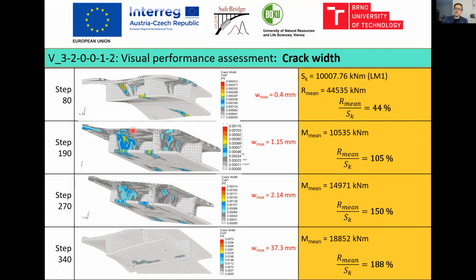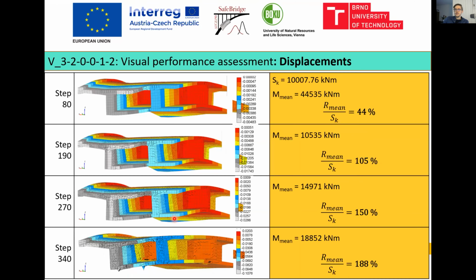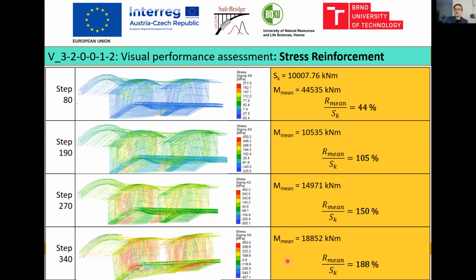You can see here that at step 80 the shear cracks are dominant, but then the concrete slab at the bottom becomes more and more of a weak point. It is also the point where the whole structure collapses. We also did this with displacements. You cannot see that much, but you can see the difference between models 4.3, the green, and the pink models, which were interesting, where half of the structure was a linear elastic material. We also looked at the stress of the reinforcements, and here you can see the same picture as with the cracks.